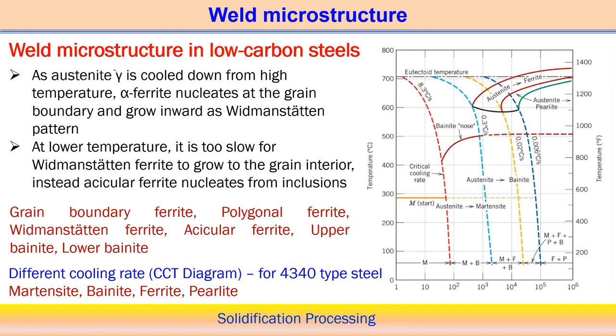So here you can see the weld microstructure in low carbon steel. In this case the austenitic, the gamma phase, is the high temperature phase, and it cools down from the high temperature. When the austenitic phase cools down, usually alpha ferrite nucleates at the grain boundary and grows, and it can create the Widmanstatten pattern. This particular morphology or structure is usually formed when cooling down from the high temperature.